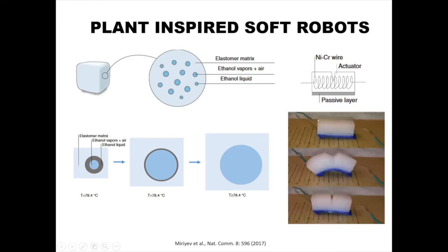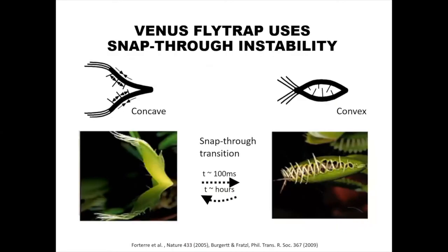And what you can see here is that the material is basically a foam, a composite between elastomer and ethanol. You push a wire through, and then you have this actuation and bending motion. Here the big challenge is that we have these soft materials, but like in the first talk, we have a material that's gas permeable. So we are losing the active liquid, the ethanol, during actuation. So this is a challenge for this device.